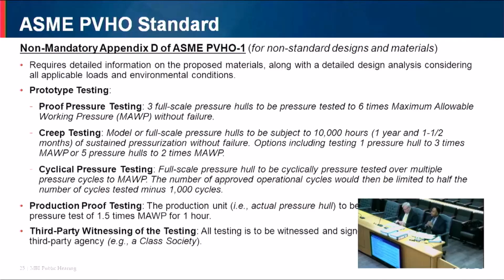So after the creep testing, the next thing is cyclical pressure testing. This is basically a fatigue test. So then you take a full-scale pressure hull, and you will cyclically pressure test the hull for a number of pressure cycles. The approved operational pressure cycles will basically be half the number of cycles you tested minus 1,000 cycles. Okay, so that is how you get the fatigue life of the hull. So once you conduct the prototype testing, you have qualified the prototype. So the next thing is you build the production unit, and thereafter you'll do a hydrostatic pressure test to 1.5 times the design pressure, and then you'll maintain the pressure for 1 hour.